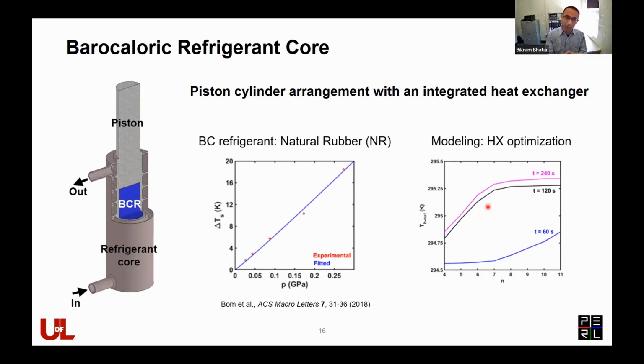That's a key component. We picked natural rubber as our barocaloric material, which has been demonstrated to be a pretty good barocaloric material as reported in this experimental result shown from the literature. You can see if you apply around 250 megapascals of pressure, you get around 15, 16 Kelvin temperature change, which is pretty good. The second thing is the heat exchange from this core and into this core.